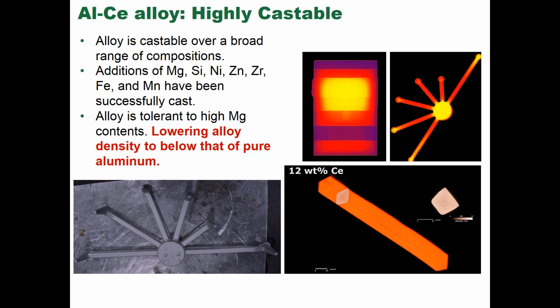We've cast over 30 different variations of the alloy. Some have been uncastable. Most have been castable. Some have developed pretty poor mechanical properties. Some have developed quite extraordinary mechanical properties. We'll discuss more, but the alloy is tolerant to really high mag contents. And so people are concerned, well, you're adding cerium, which is a high density material, that is going to make my casting way heavier. That we can completely counteract by adding enough magnesium to bring the density down to that of pure aluminum.